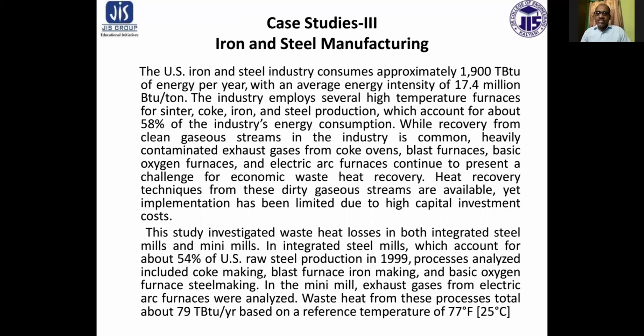They investigated waste heat losses in both integrated steel mills and mini mills. In integrated steel mills, which accounted for 54% of raw steel production in 1999, processes analyzed include coke making, blast furnace iron making, and basic oxygen furnace steel making. In the mini mill, exhaust gases from electric arc furnaces were analyzed. Waste heat from these processes totals about 79 trillion BTU per year, based on a reference temperature of 77 degrees Fahrenheit, that is 25 degrees centigrade.